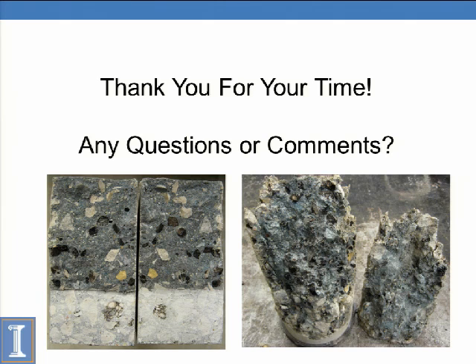Would you expect the conclusions to differ, though, if you just use straight cement? Absolutely. I would probably say that the permeability would be higher. The chloride ion penetration test would give you higher results, because in using slag and fly ash, we really densified the microstructure. I can get into the cement chemistry, but you guys probably may not be interested in that. But in the end, if you use slag and fly ash at a later age, which is when we tested it at 56 days, you will have a denser microstructure, and typically a stronger concrete at later ages. At early ages, by using a ternary blend, you may have lower strengths than a straight cement mix, but the late gain is much better than plain cement.